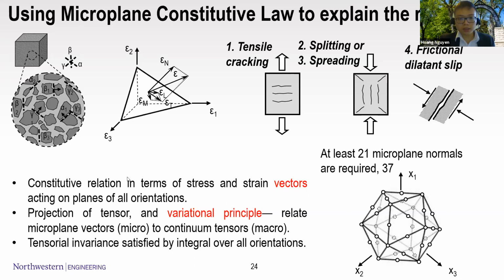And this constitutive law uses the relation between the stress and strain vectors to model the behaviors, and then turns the stress vectors into the stress tensor by the variational principle. Within this framework, at least 21 microplane normals are required to get a certain level of accuracy. However, in this study, we used 37.